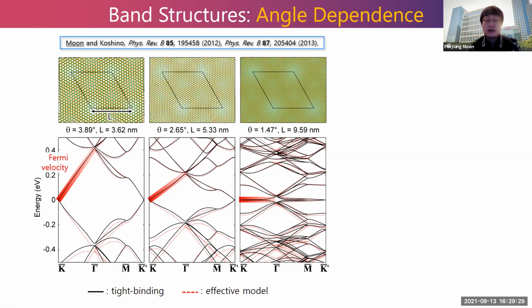An electron in single layer graphene can only have a single fixed velocity of 10 to the 6 meters per second. An electron can never change its velocity and never stops in monolayer graphene. But by simply stacking two layers of graphene and slightly twisting them, we can change the velocity a lot and even stop the electron.